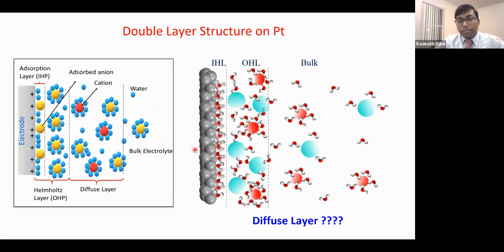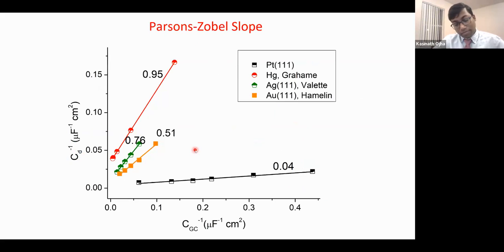Again, if you check the theory versus experimental result plot for mercury, it is generic. For silver and gold, it is again the 111 surface, right? Equivalently for platinum, it is the 111 surface. No. Mercury is liquid, and you can get a really pure surface; that time mercury was possible because with a liquid the surface remains flat, and the electrolyte is on top. But this was done in the 1940s, and at that time you wouldn't be able to generate really highly oriented crystal facets of platinum, silver, or gold at all. So these were done much later.